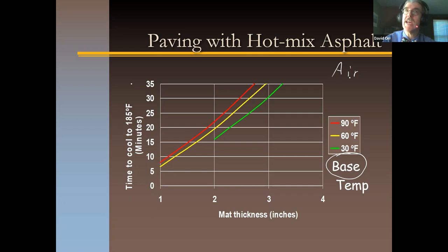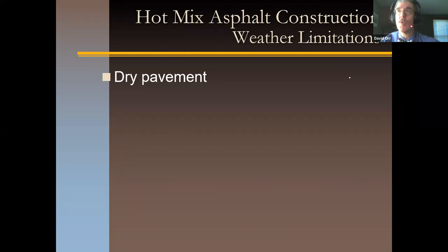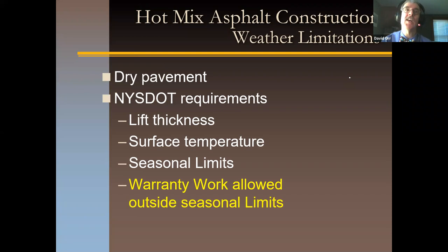If it's a cool day, you've got to do that. So that's why we have weather limitations that come into play. Now, the number one thing you've got to do, by the way, this is not just temperature getting compacted: the pavement really needs to be dry. If you've got a lot of water on the surface, you're not going to get a good bond, tack coat or no tack coat. And the DOT has a whole bunch of requirements in their spec that involve lift thickness, surface temperature, and some seasonal limits.